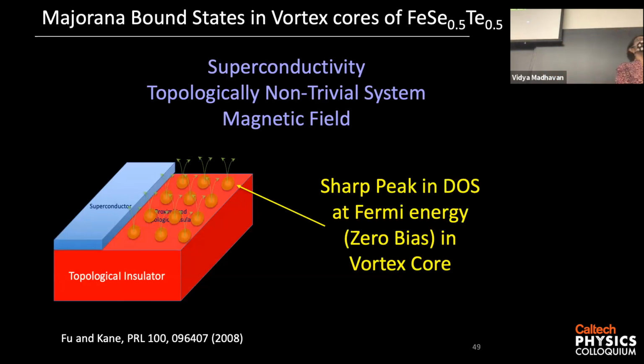Okay, so now let's turn on a magnetic field and ask, what do we expect to see? When you turn on a magnetic field, what you expect to see are vortices, and inside each vortex, if this is topological, if this is what we think it is, you should see a sharp peak in the density of states right at the Fermi energy, and that sharp peak is your Majorana bound state. Okay, so now let's look at what we see.